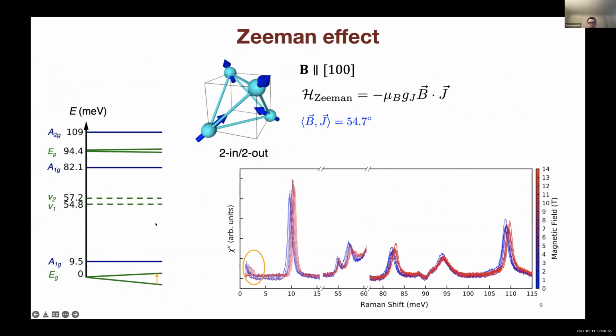We also applied a magnetic field along the 100 cubic direction up to 14 Tesla at about 5 Kelvin. The local spins are aligned along the 111 easy axis, forming this two-in-two-out spin ice configuration. The Zeeman effect will split the doublets as the magnetic field increases. And in this spectrum, I present the field dependence of the crystal field transitions.